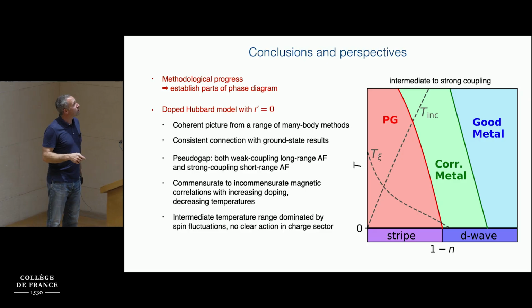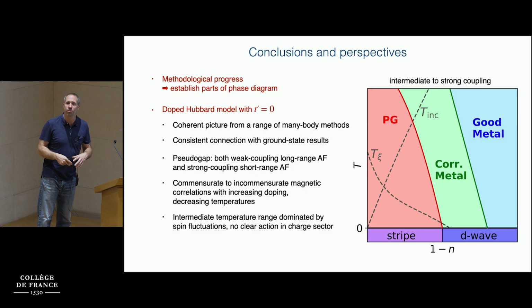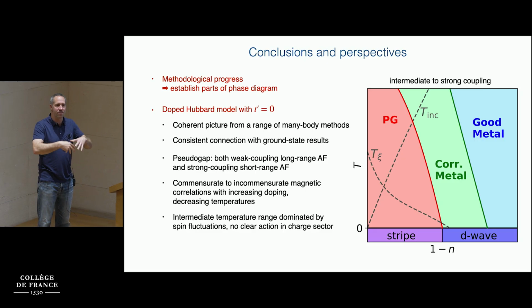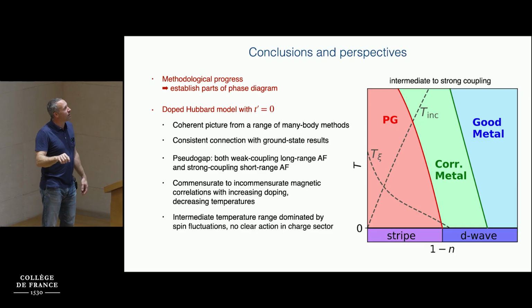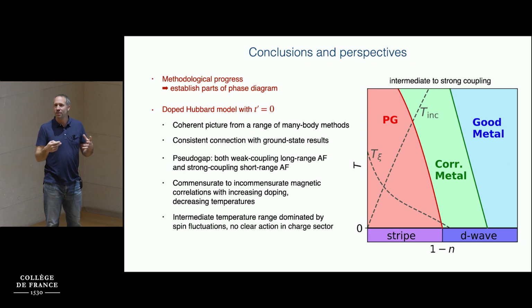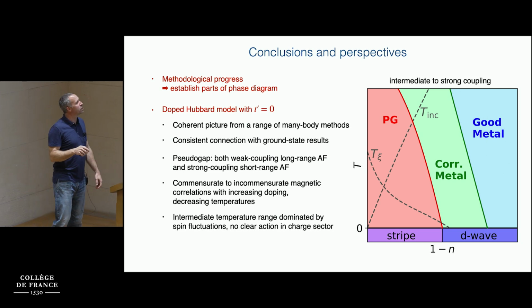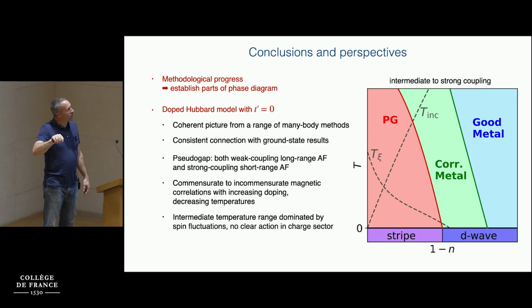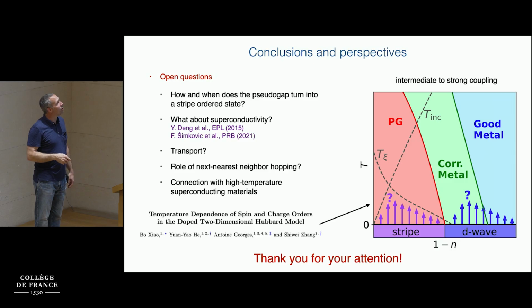So to conclude, I want to say that there's been a lot of methodological progress. I've shown here results from Diagrammatic Monte Carlo, but there are other methods, and they now give us a coherent picture of what's going on. I think it's clearly established that in a Hubbard model, we do have a pseudogap regime whose origin, at least at intermediate temperature, is definitely spin fluctuations. This pseudogap regime extrapolates exactly to the place where in the ground state we see a stripe. As we increase the doping, we have first a correlated metal with a modified Fermi surface and eventually a more conventional metal.